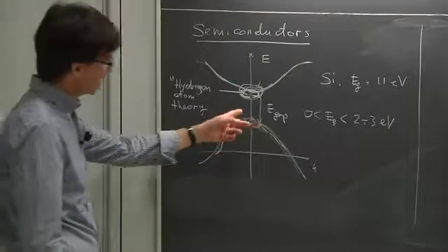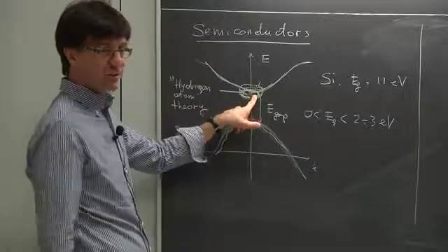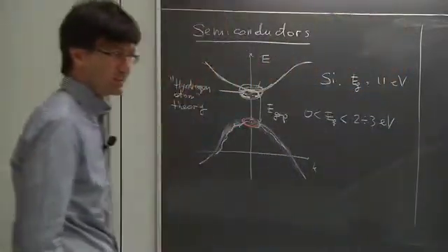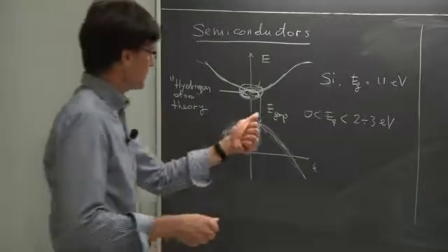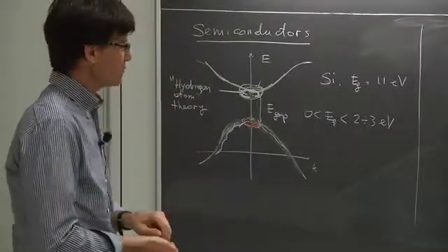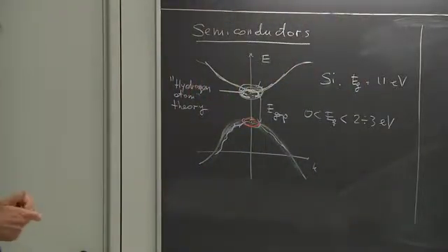I want to have a crystal with a large number of missing electrons here and no electrons here. Well, I play the same game with aluminum. I throw a large number of aluminum atoms in during my growth. And I can play with this concentration because each atom is contributing one electron. So if I throw in a given concentration of aluminum or phosphorus in my growth, I will have a given amount of carriers in my material.